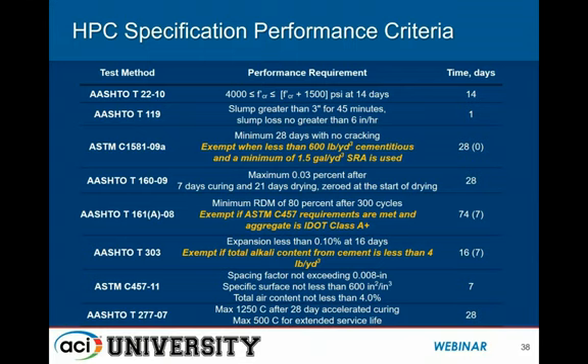This wasn't a popular idea to start with, but the way that we wrote it, if you look carefully at the equation at the top, the minimum required by design was 4,000. If you submitted a trial in the qualification process, you were getting 6,000 PSI at 14 days. That meant that your allowance for your trial was going to be 6,000 plus 1,500. So that would essentially give you a range when you get out into the field and actually employ this specification. It meant that you'd have a range of 4,000 to 7,500, and that gave enough wiggle room. And in many cases, we haven't had issues with this, and in many cases, it's been no problem at all. The slump loss was considered as well. This is another constructability issue that was emphasized, trying to make sure that none of the strategies employed caused a problem on the construction side.